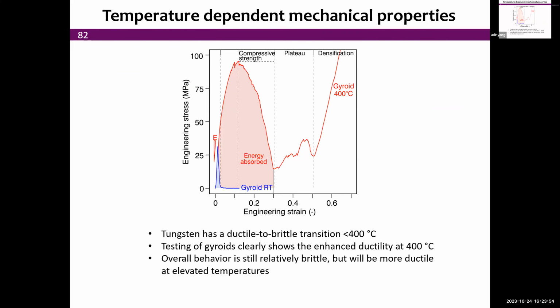porosity. And you see the stress-strain curves here in compression, of course, we see that at room temperature in blue, the gyroid is relatively brittle. Since we are below the ductile to brittle transition temperature of tungsten, the material is as brittle as a ceramic. So it goes to about 20, 30 MPa and then fractures miserably. At higher temperature above the DBTT, we now have a much higher strength and then a rather graceful fracture without complete shattering. And so the energy absorbed is much larger in that particular case.